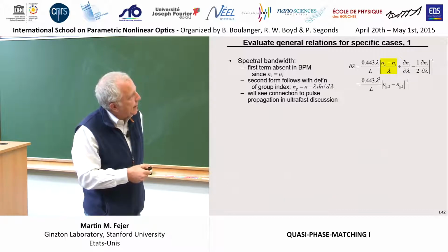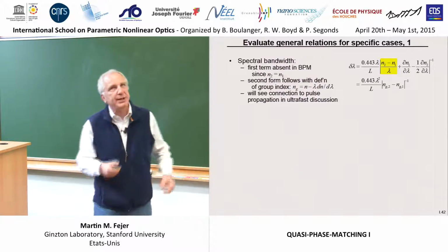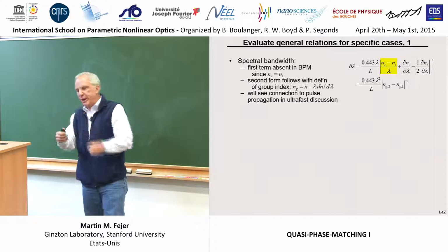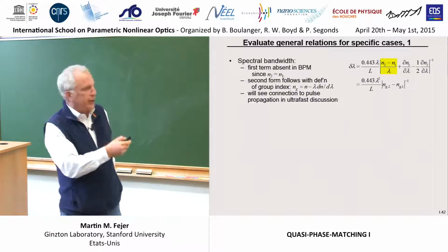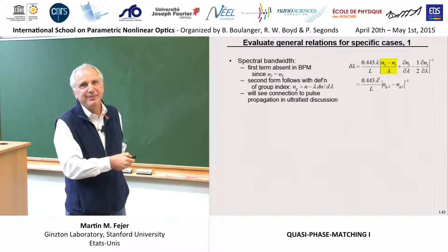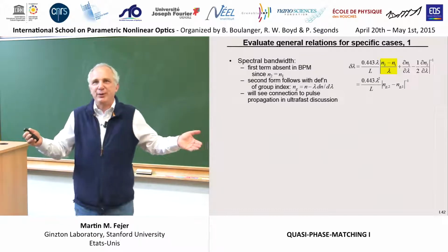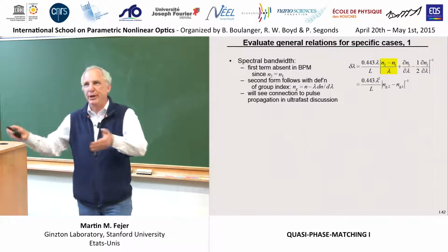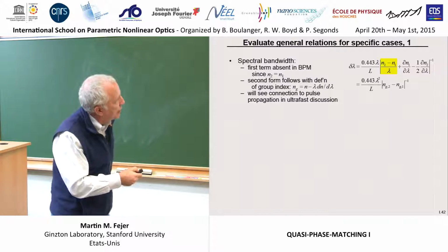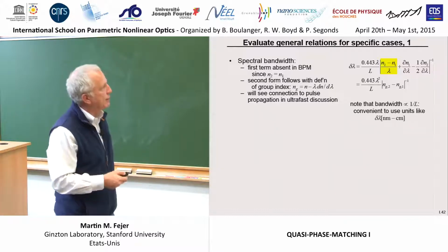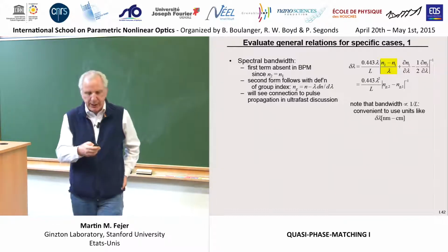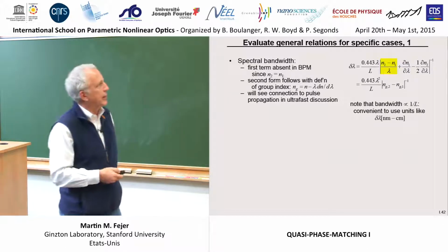also contains this thing, which is the difference between the refractive indices at the harmonic and at the fundamental. And in a phase-matched interaction, of course, this vanishes. But we aren't phase-matched. We're quasi-phase matched. So there is a difference between N2 and N1. So this term is going to appear in the quasi-phase matched case, unlike the birefringently phase-matched case.